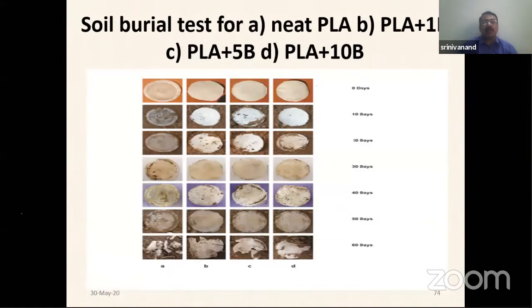And finally we did the soil burial test, because we wanted to make sure that even after the incorporation of inorganic material and organic biocide, we don't want our PLA to lose its original biodegradable behavior. So we did the soil burial test accordingly, and we found that the biocide loaded and inorganic system loaded PLA has a slightly lower degradation rate. However, it degrades at a later point of time. So the neat PLA undergoes degradation very fast, whereas the hybrid PLA systems do undergo degradation, but at a slower rate. But still, they are capable of undergoing degradation. So we made sure that we don't compromise the biodegradable behavior of our products.